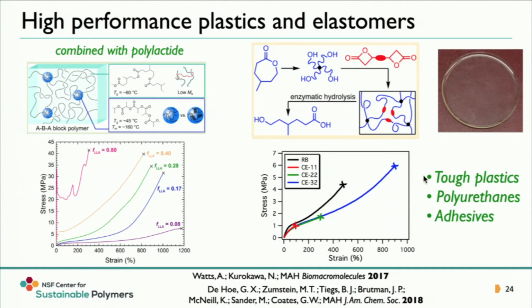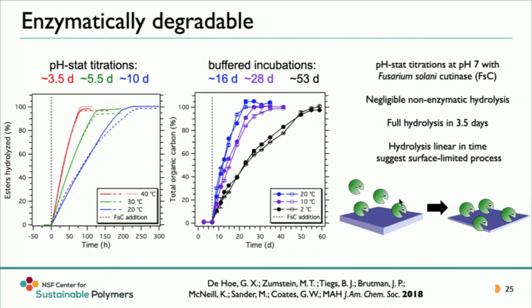For these elastomers and tough plastics, we also have efforts in polyurethanes and in adhesives. What we then did with those materials is we studied their enzymatic degradation. So these aliphatic polyesters are actually susceptible to enzymatic degradation. And what we showed is that when put in water, not much happens over the time frames that we were interested in, but once we add cutinases, the degradation starts happening quite rapidly.